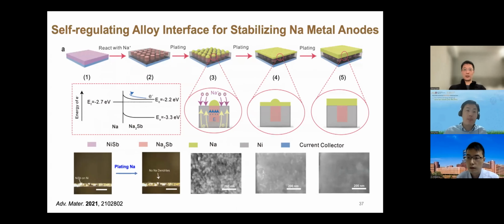can stabilize the sodium metal significantly by forming this so-called heterojunction-like structure. And once you form this heterojunction-like structure, the deposition of sodium metal will go to a competing structure where first the sodium will deposit onto this island-like sodium antimony, and then they will deposit on the nickel surface because the nickel is more conductive electrically, right? So they will compete and self-smooth, and at the end of deposition, they will form a very, very smooth anode, okay? And we don't really see a dendrite formation.